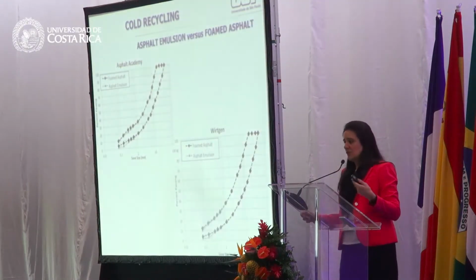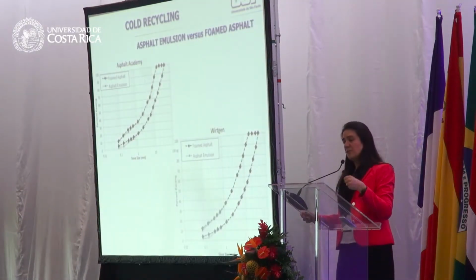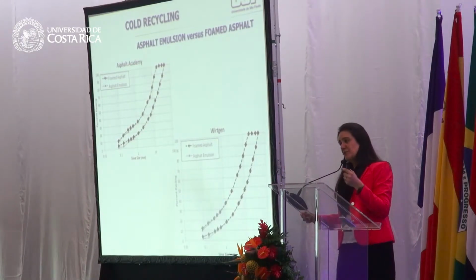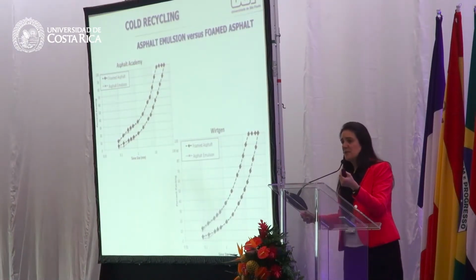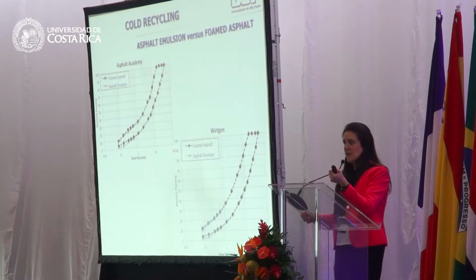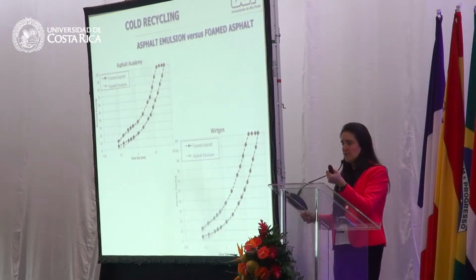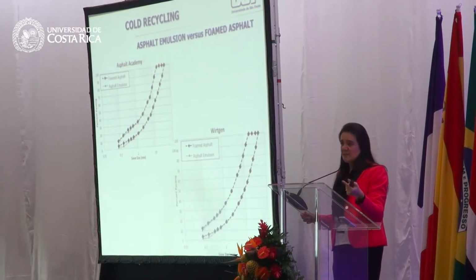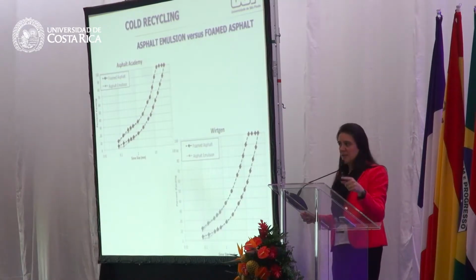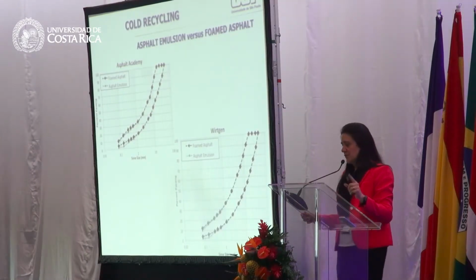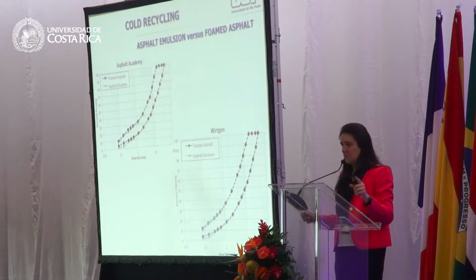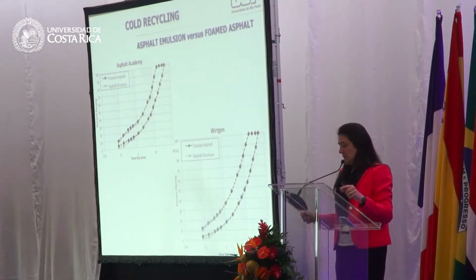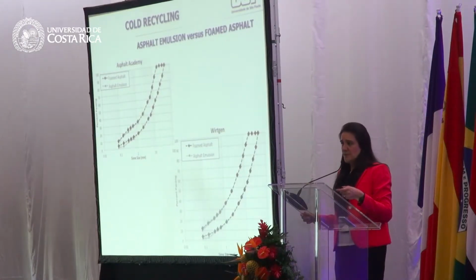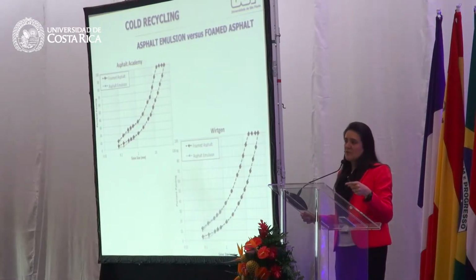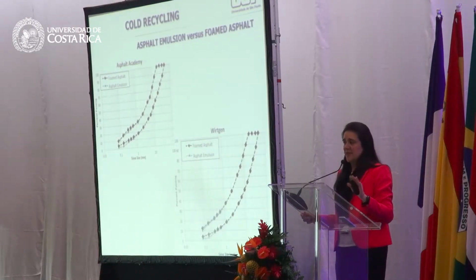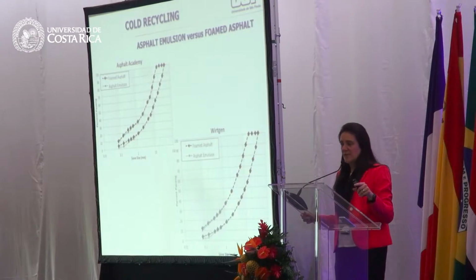Regarding the gradation of this type of mixture, because in the foaming process you need these fine particles to stick with the foamed asphalt, you need more fines. So I've put in here two different gradations from the Asphalt Academy and from Wirtgen. And in both of them, if you are using an emulsion, you can have fewer fines in your aggregate gradation.